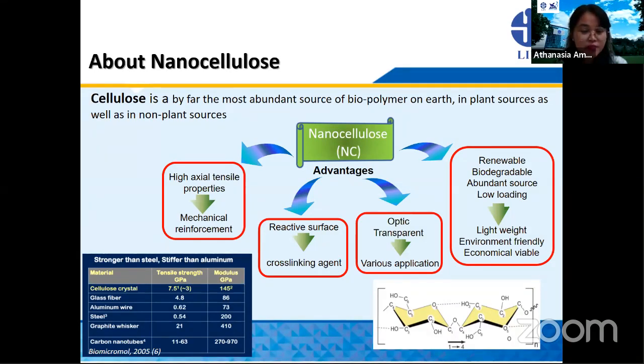First of all, these materials offer high tensile properties. In fact, there are so many reports showing that the cellulose nanocrystal, particularly, can exhibit tensile properties even 8 times stronger than steel, which is a very valuable property for mechanical reinforcement in nanocomposites. The second one is the presence of the hydroxyl groups on the surface of the nanocellulose, which can also give a benefit for easy functionalization, especially for cross-linking with other chemicals, both inorganic and organic matter.